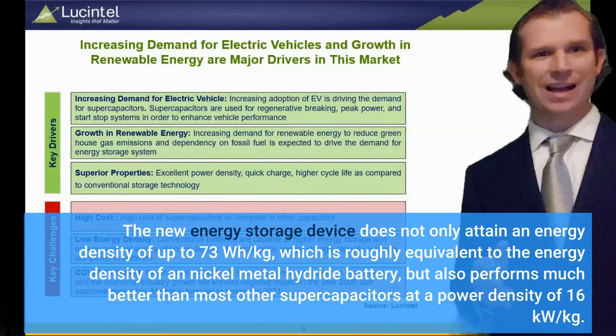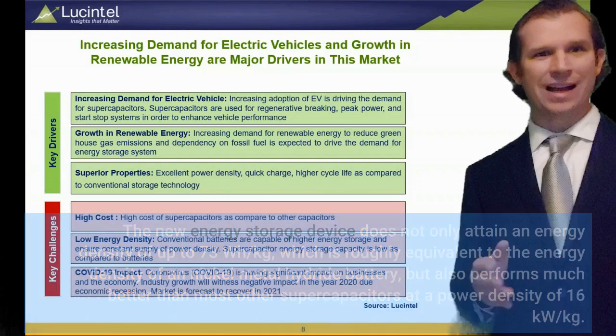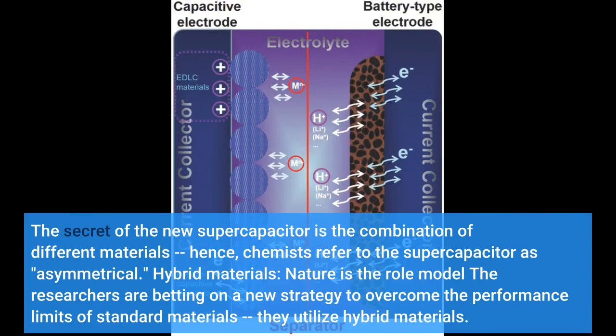The new energy storage device not only attains an energy density of up to 73 watt-hours per kilogram, which is roughly equivalent to the energy density of a nickel metal hydride battery, but also performs much better than most other supercapacitors at a power density of 16 kilowatts per kilogram. The secret of the new supercapacitor is the combination of different materials, hence chemists refer to the supercapacitor as asymmetrical.